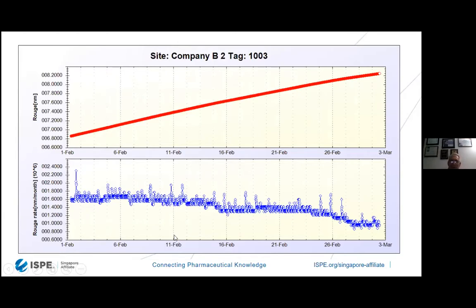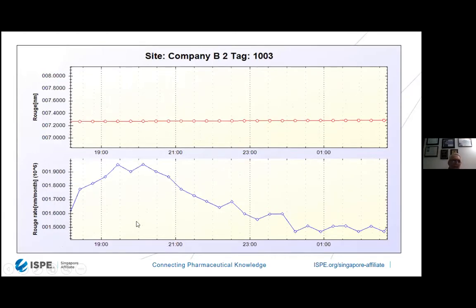What is happening here? Well, this is a water system running at 50 degrees Celsius during the day, but at night, they actually do a sanitization. So at 7 o'clock at night, they take it up from 50 degrees C to 80 degrees C. They leave it there for 1 hour. And then at 9 o'clock at night, they let it go back down again. But you can see that the actual accumulation of rouge is very, very small, even though the rouge rate goes up and down cyclically based upon that particular level.